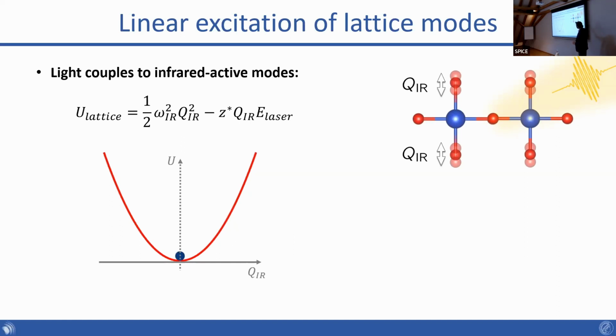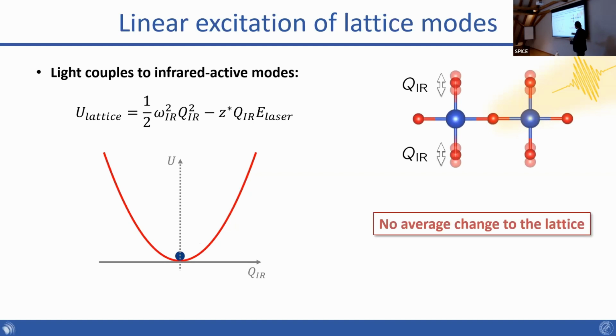I'm going to vibrate the atoms corresponding to the phonon displacement coordinate. And essentially, this is a little bit like flicking a ball on a pendulum. I'm going to essentially displace the atoms along this infrared active coordinate. They're going to ring down with some natural frequency and some damping rate. Okay, but the problem is that there is essentially no average change of the lattice when you do this. It's vibrating back and forth at some several terahertz frequencies. And so if we're looking at longer timescales, we won't see any real change to the crystal structure. So we need to do something different.